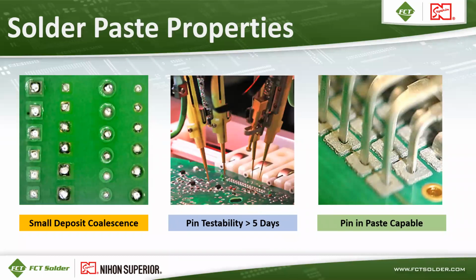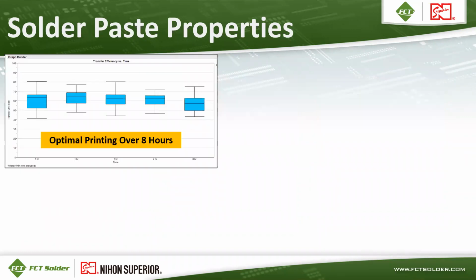And of course, we also know that a lot of through-hole components are becoming less common, but there are still cases where surface mount technology is being soldered along with maybe 1 or 2 connectors that are through-hole. So it's advantageous to have a solder paste that can be printed for those through-hole components and reflowed at the same time as the surface mount components without dripping out of the hole, giving you a proper solder joint and proper barrel fill. So pin and paste capability is important for solder pastes as well.